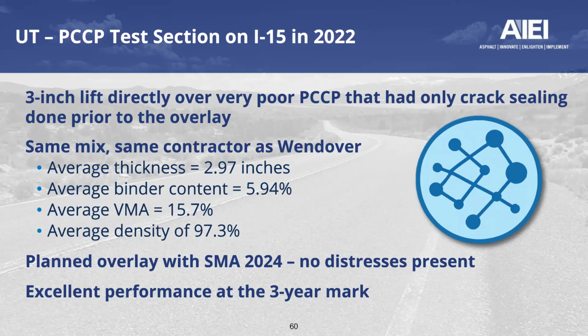And again, it easily achieved densities above 97% as an average. And the spread on that, by the way, was also quite good. There was a planned overlay which they executed in 24, so about 1.5 years, almost 2 years in to the trafficking of this location.